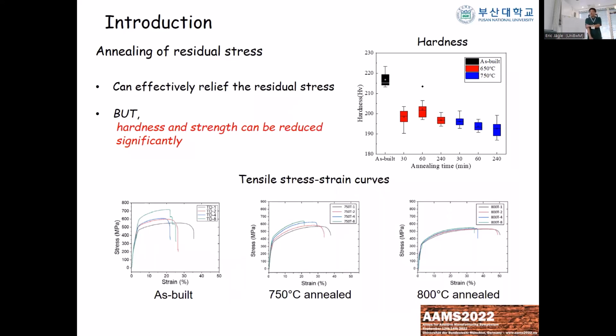So if the component is very sensitive to dimensional error, for instance like the impeller or the heat exchangers with joints, then to prevent the distortion we normally have to go for heat treatment. The annealing heat treatment can effectively relieve the residual stress. When we go up to high temperature for a long time, we can more efficiently remove the residual stress. But the hardness and the yield strength are normally reduced when we increase the heat treatment temperature and make the heat treatment time longer. So there will be some optimum condition where we have a small enough amount of residual stress that we don't have any distortion problem, but we keep the required hardness and yield strength.